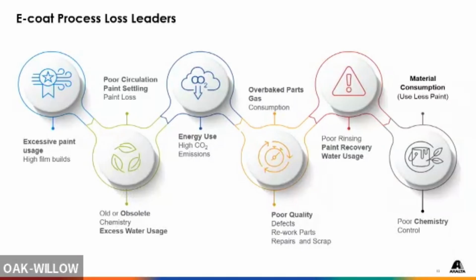The other place I see problems all the time is with overbaking parts. I think we have this mentality in the OEM world, set it and forget it, right? Ecoat is automated. If you maintain your bath chemistry, if you have precise control of your voltage, you will end up with the correct amount of microns on those parts every time. It's very repeatable. But I think we take that mentality and apply it to everything, right? So we set it and forget it. We know the oven, the heavy metal areas need to be at least 160. So let's set the ovens to 200 C, overbake the exterior just to make sure we have that 160 on the heavy metal hinge.